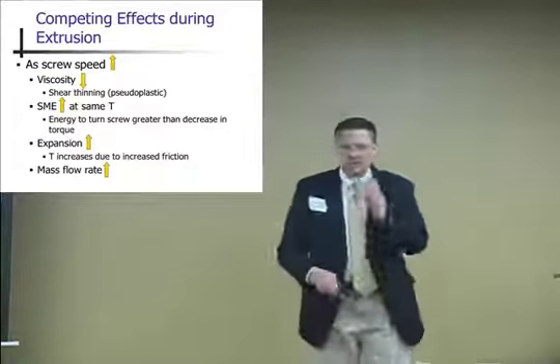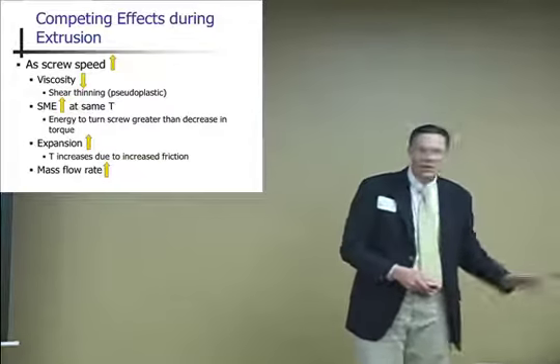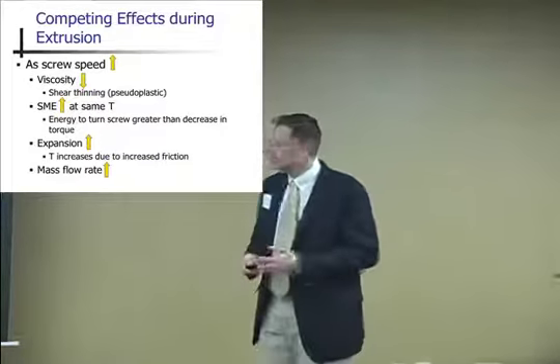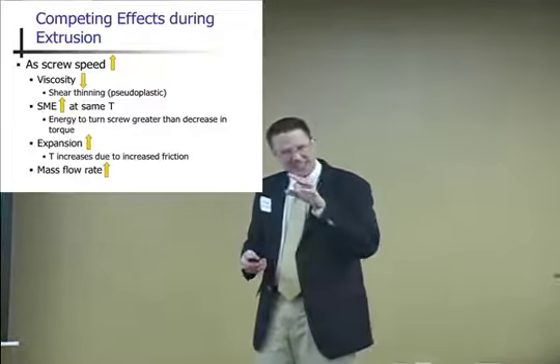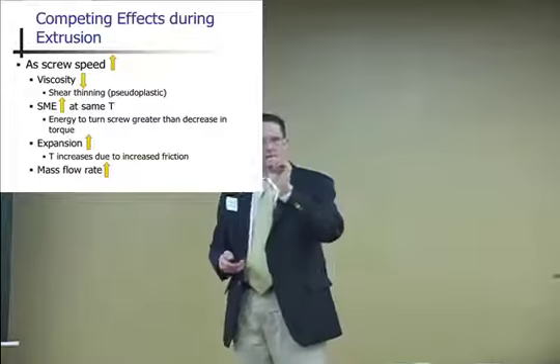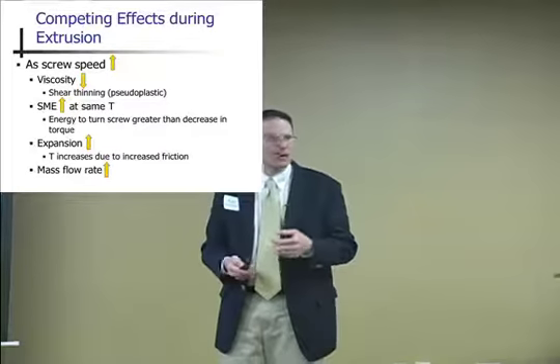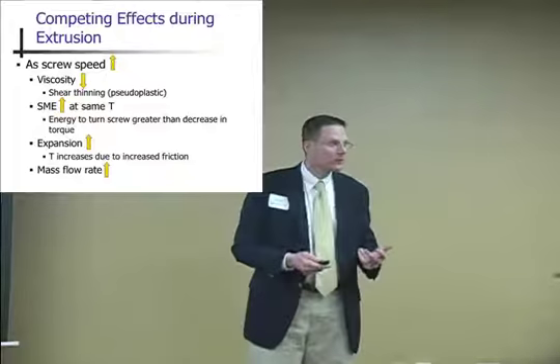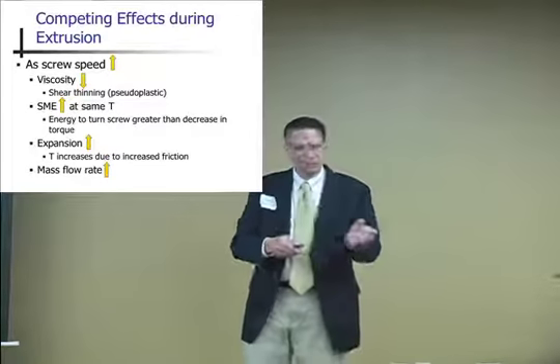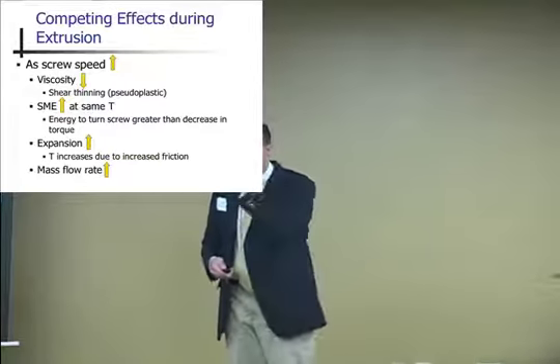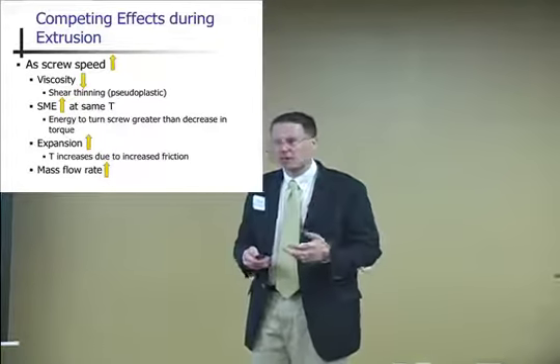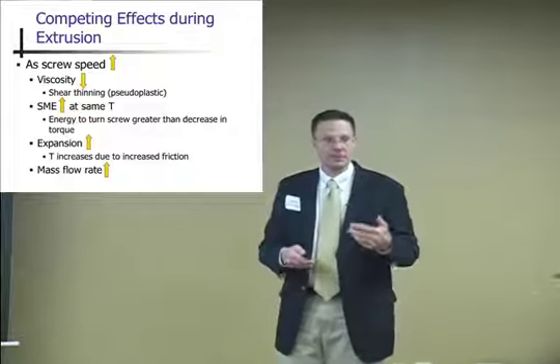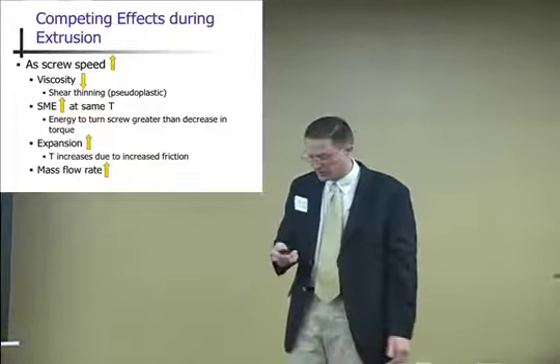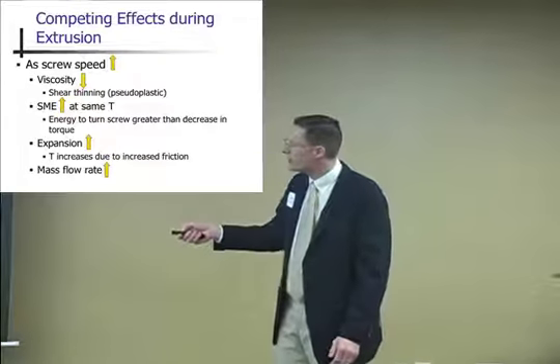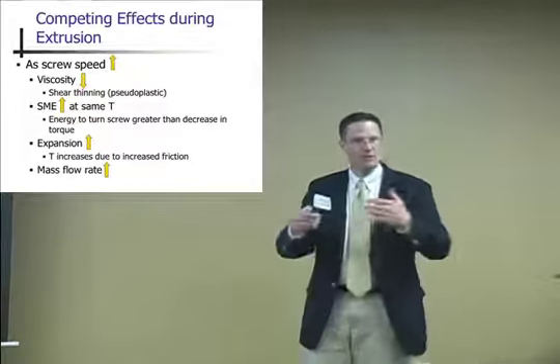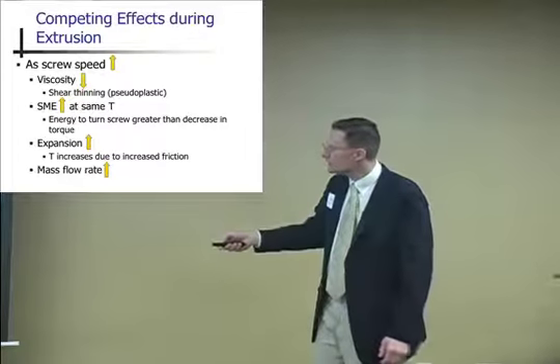So competing effects. We talked about a lot of things, but the juggling act is what we're trying to really worry about. If somebody says, I can't get my pellet to have floatability of more than 10 seconds or 20 seconds, or my pellet's not water stable, let's go tweak something in the process. Well, you change one thing, everything starts to fall apart. So basically, as you increase your screw speed, your viscosity is going to go down because it's shear thinning material or pseudoplastic material. As your screw speed increases, your SME is going to increase because it takes more energy to turn that screw faster. Your expansion should increase.